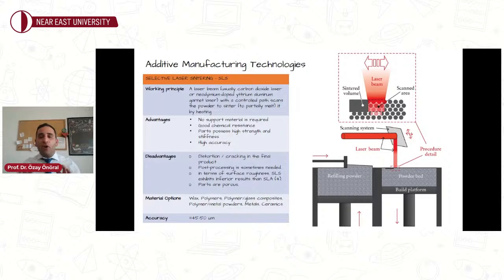But over here, please focus: we are not completely melting all the metallic powder in this technology. High power of the laser allows the fusion of powder through molecular diffusion, guys. After scanning, the powder platform is lowered by a single layer, typically 20 or 100 micrometers in most of the devices. It can be changeable in accordance with the device. A new layer of powder is dispersed on the platform, again cured by the exposure of the laser, and the whole process is repeated until the completion of the 3D model.